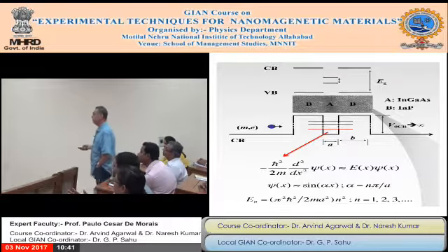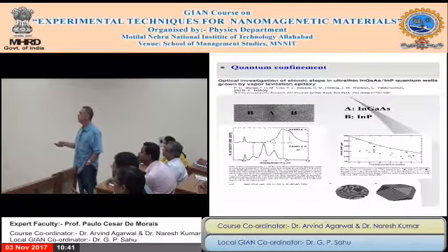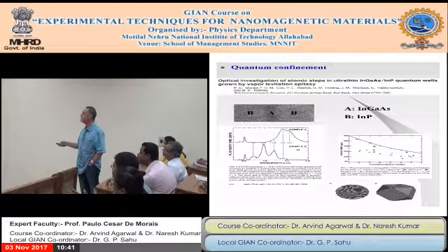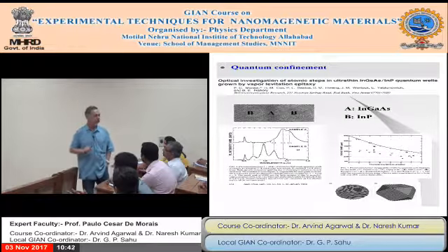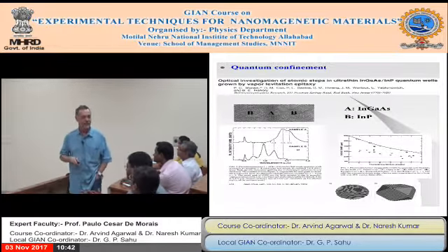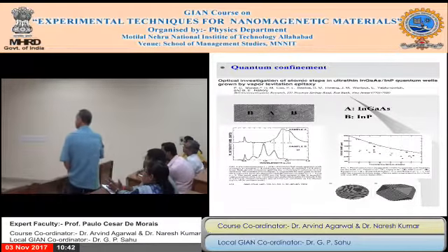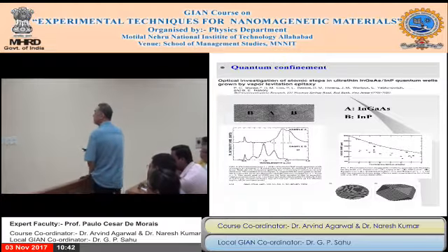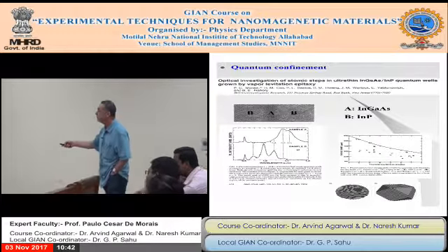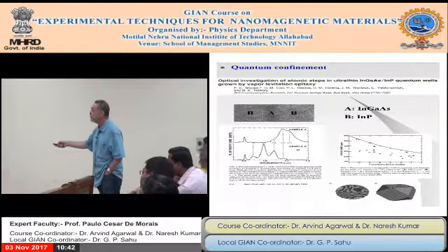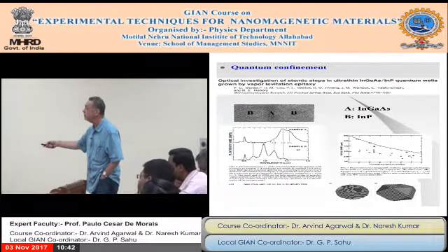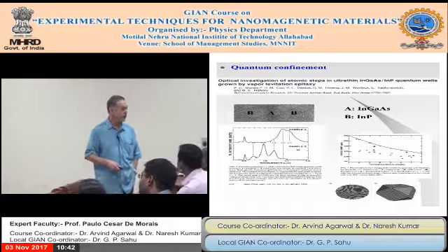This is the real photoluminescence spectra of different samples with different thickness of the quantum well. And this is experimental. So you can see those peaks, like this one. This is a peak. You can extract this peak position in wavelength and transform that into energy.